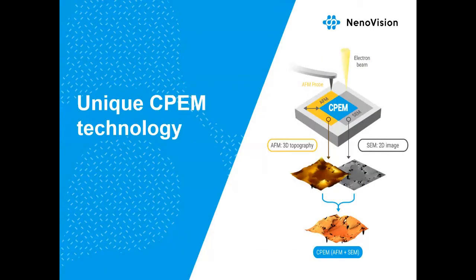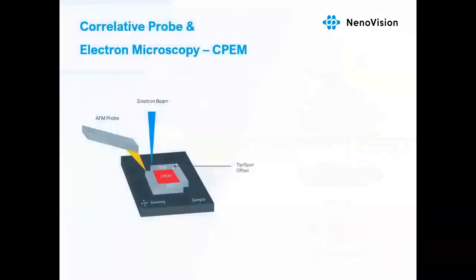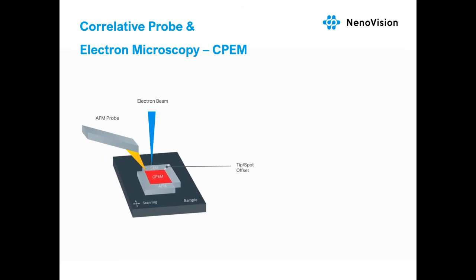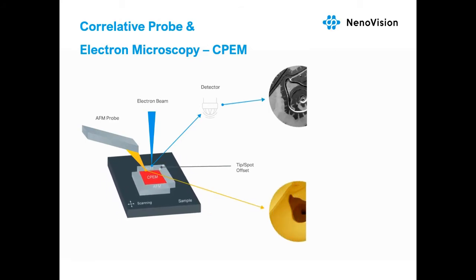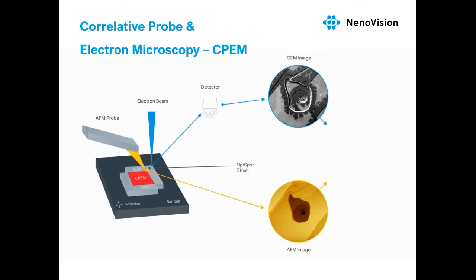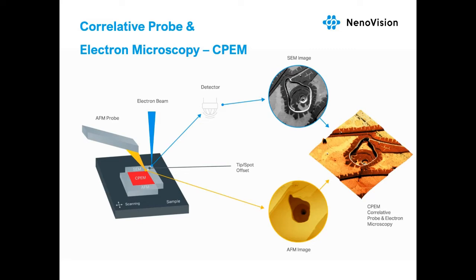As we were talking about different techniques and different applications, we didn't quite mention how the unique correlative probe and electron microscopy technology, shortly CPEM technology, actually works. On the sample, the electron beam points very close to the AFM probe, the AFM tip. During scanning, the AFM tip and the electron beam remain static, so the sample is being scanned only by the LiteScope piezo scanner. This enables simultaneous detection and acquisition of AFM and SEM signals at the same time, in the same place and under the same conditions.